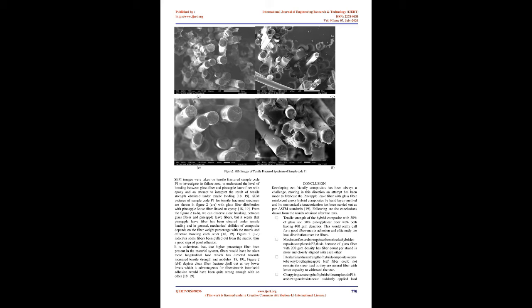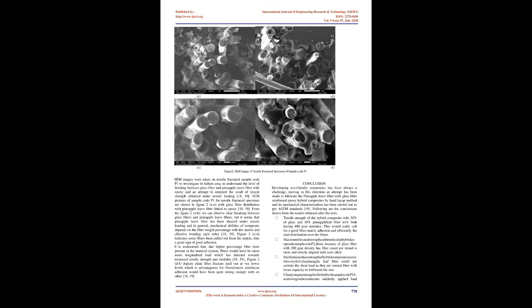Flexural Properties: The flexural test result shown in Table 1 indicates that the flexural strength and flexural modulus of sample code P2 has 119.24 MPa and 10,762.25 MPa, good enough when compared to others. The laminate with 200 gsm density in combination with pineapple leaf fiber reinforced epoxy composite has shown good resistance to flexural loading. The three-point bending load on sample code P2 showed the breaking of the matrix first, followed by fiber cracking. The sample after the test was carefully examined, which revealed that when load was acting in perpendicular direction, the top layer fiber may have undergone compressive deformation and the bottom layer would have stretched out, leading to fiber breakage.